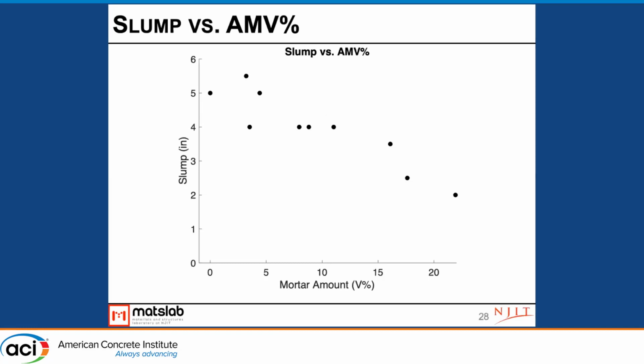So as we increase our mortar volume percentage, our slump is decreasing, which makes sense if you think about that adhered mortar phase. It's a very rough phase, and it contributes to lower workability. Even if it's been brought to an SSD condition, it still has a pretty big effect on the workability of the system. So I found this result to be pretty interesting, and it definitely confirms some other findings in relation to decreased workability with increasing recycled concrete aggregate replacement in an RCA system.